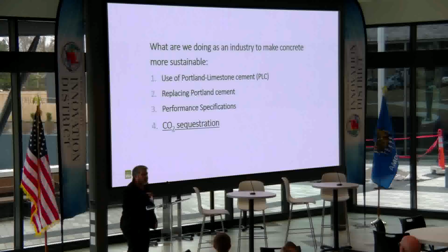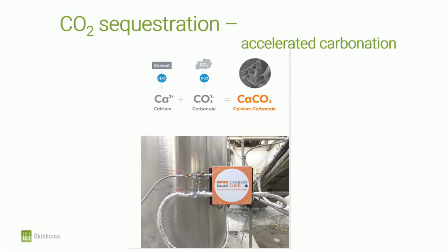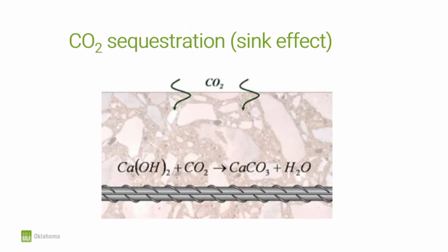So finally, the CO2 sequestration that we've been talking about, how does that look? We have two different types of sequestration of CO2 in concrete. The first one is during the fresh state. There are companies out there that have come up with a technology to inject CO2 into concrete. This CO2 will help us reduce about 5% of that Portland cement, therefore reducing the global warming potential. The other thing is that during the life cycle of our concrete, we're going to have what we call a sink effect, where the concrete surface, just by being exposed to CO2, is going to start sucking that into the concrete in a phenomenon we call carbonation.